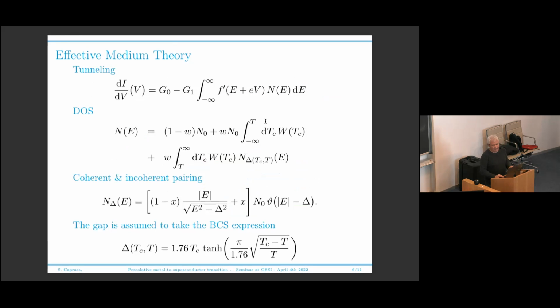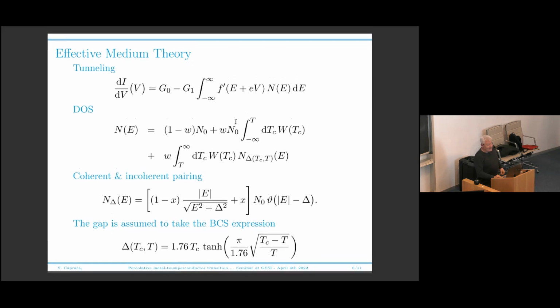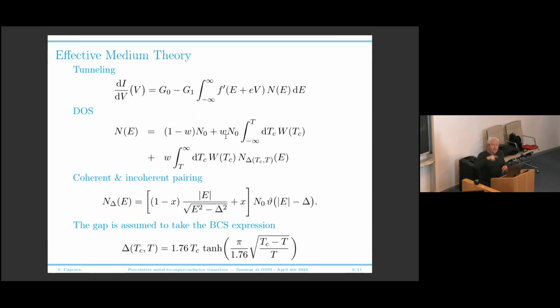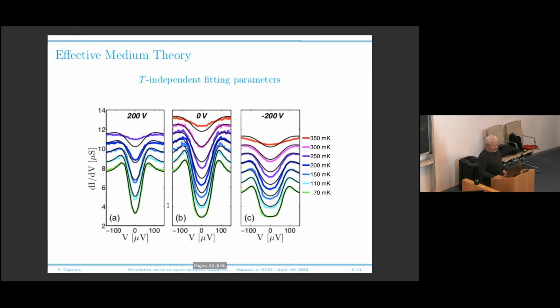And then here are the details of the calculation. Maybe these are a bunch of equations in effective medium. We have a density of states that is the density of states of a metal plus the density of states of a superconductor. And the density of states of a superconductor has three components. The density of states of all the islands that have not yet turned superconducting, plus the islands that have turned superconducting, plus the islands where locally the temperature is lower than the local superconducting critical temperature, but those islands maybe are too small to develop phase coherence. So there are also regions that are not phase coherent. If you fit with these three components, then you have the fitting of the data that I have been discussing here.